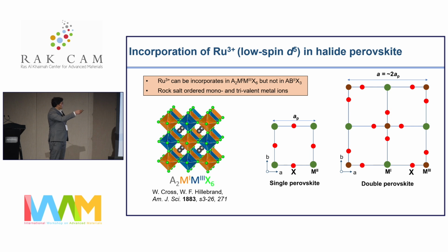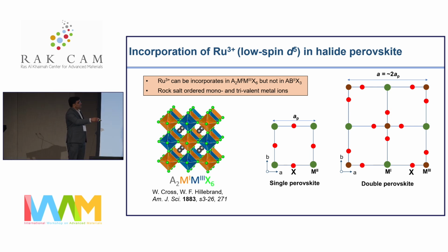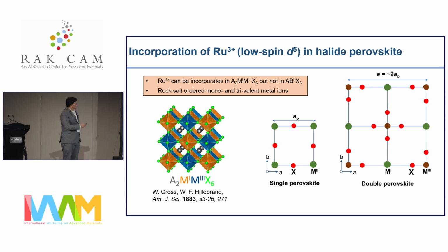Here, this type of lattice becomes stable largely because of the ordering led by the difference in charges. One is 1+ and the other one is 3+, so there is a difference of 2 here. Historically, these types of structures were known slightly before the single perovskite, about a decade before, since 1883, and the single perovskite since 1893. In early literature, this perovskite was called elpasolite, and it is still called so. Here is the diagram showing the splitting. In the monoperovskite, we split the 2+ metal site into 1+ and 3+, and choose the composition that we want to put in the lattice. So in this, ruthenium-3 should be possible to put.